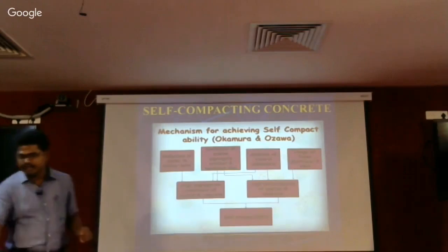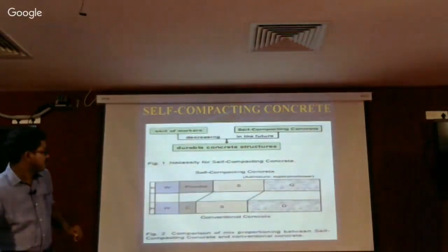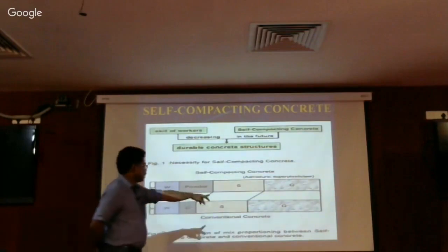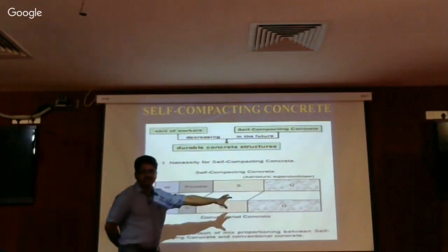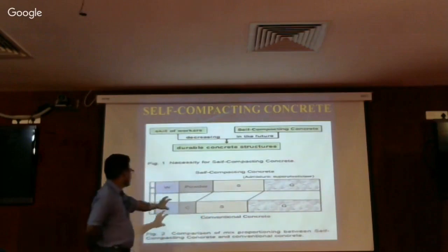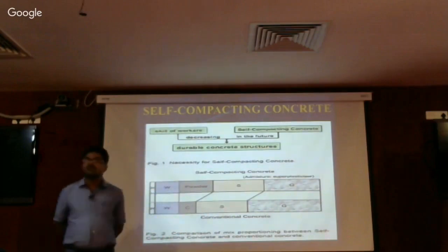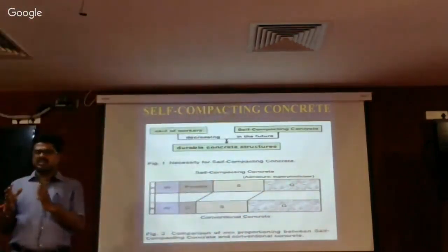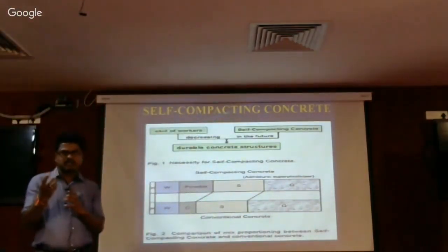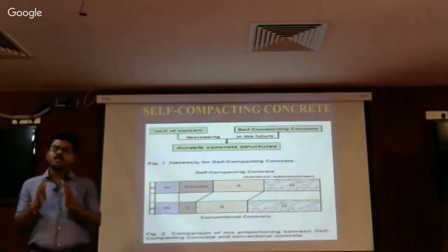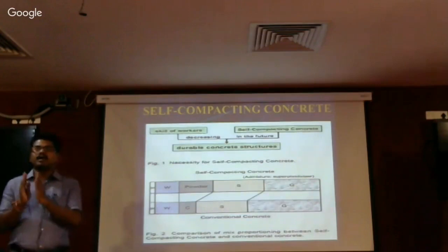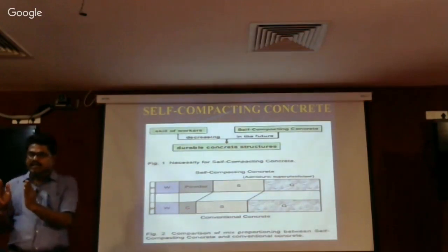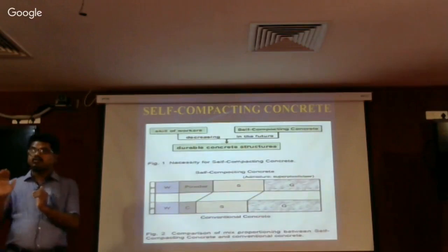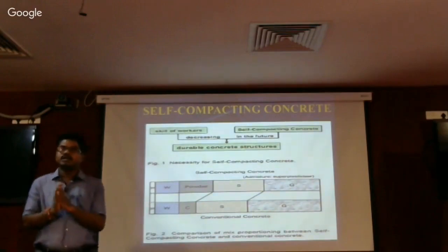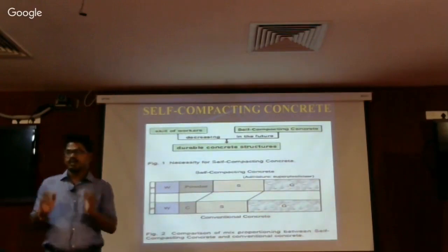For that, in SCC, the coarse aggregate content is generally much higher in our regular concrete, and similarly the sand proportion, then cement and water. So in the SCC, because if I am increasing the coarse aggregate content, automatically the voids are also increasing. That's why I am going to limit the coarse aggregate content. I am going to decrease the volume of the coarse content, but I am not compromising the strength. Whatever the minimum coarse aggregate is required for that grade of concrete, that I am fixing.